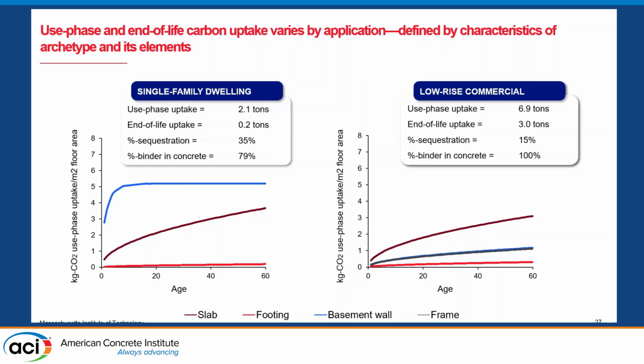So the potential per floor area is higher for the single-family dwelling, but when you sum it up for the entire unit of archetype, both the use phase and the end-of-life uptake for the commercial three-story building is higher. But then we also need to account for the binder composition to calculate calcination emissions, and then we see that the percent sequestration is actually higher for the single-family dwelling at 35% compared to 15% sequestration in the low-rise commercial structure.